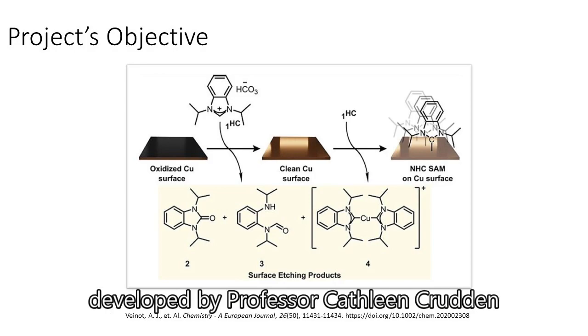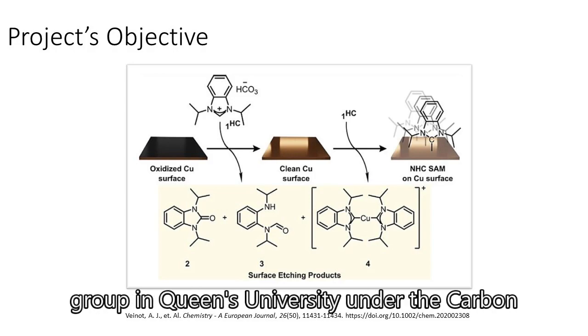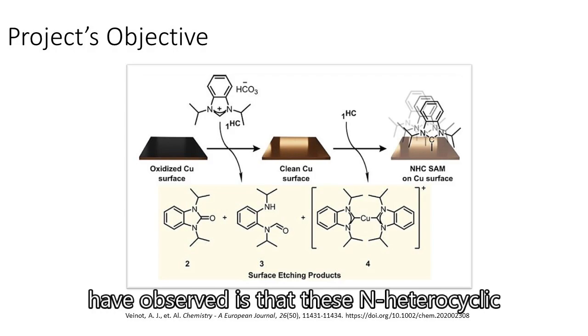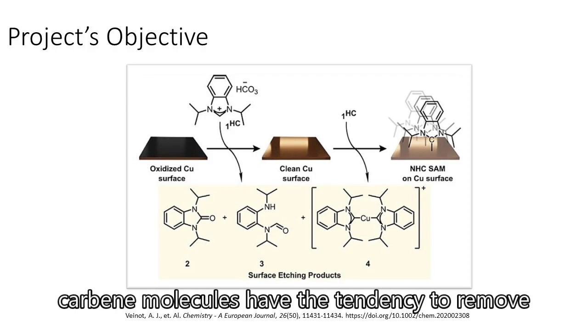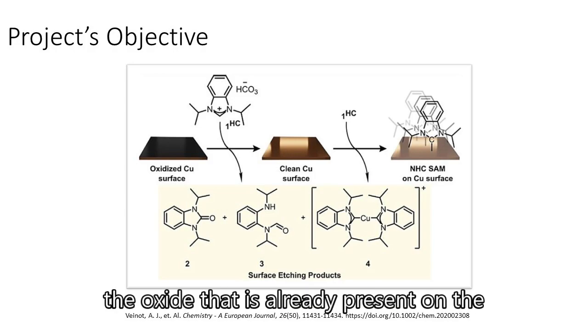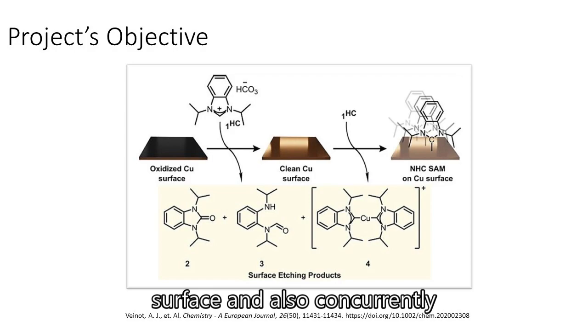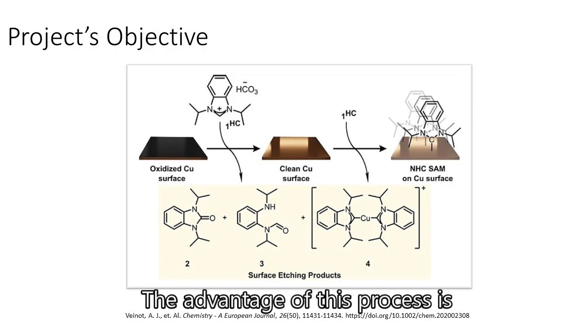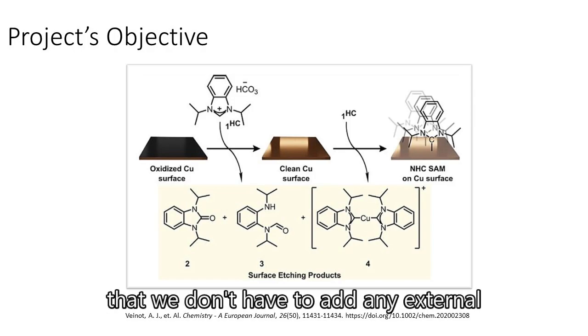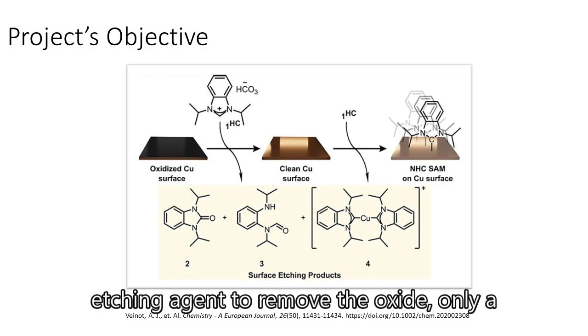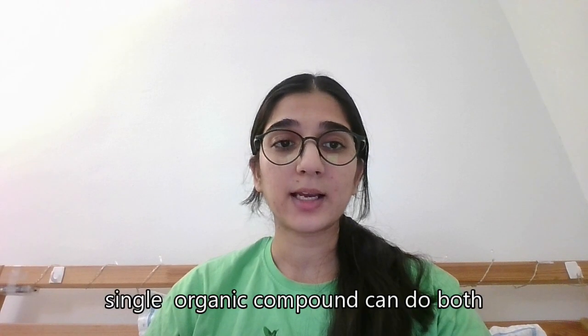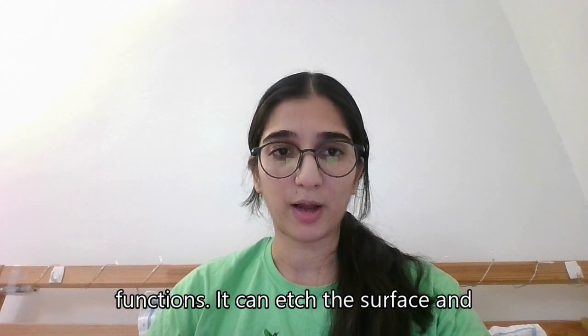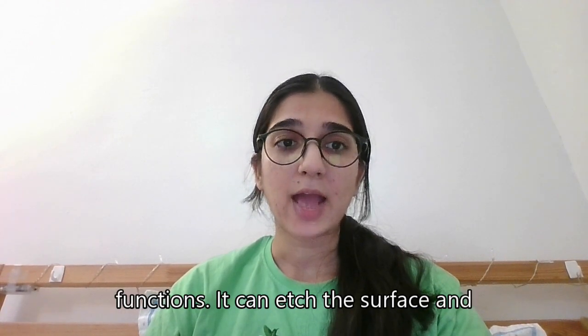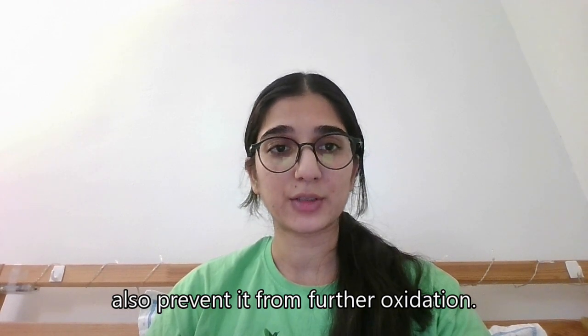This molecule has been developed by Professor Cathleen Crudden's group at Queen's University under the Carbon to Metal Coating Institute. What they have observed is that these N-heterocyclic carbene molecules have a tendency to remove the oxide that is already present on the surface and also concurrently functionalize the surface with N-heterocyclic carbene. The advantage of this process is that we don't have to add any external etching agent to remove the oxide. Only a single organic compound can do both functions. It can etch the surface and also prevent it from further oxidation.